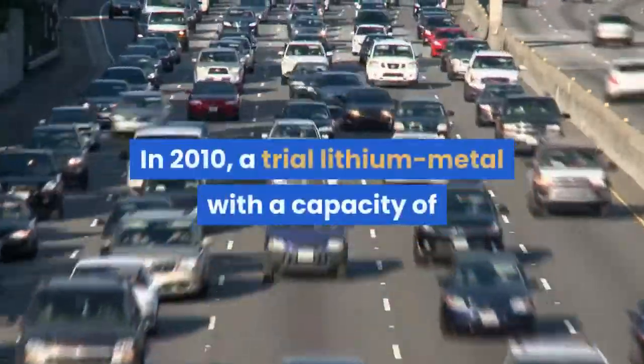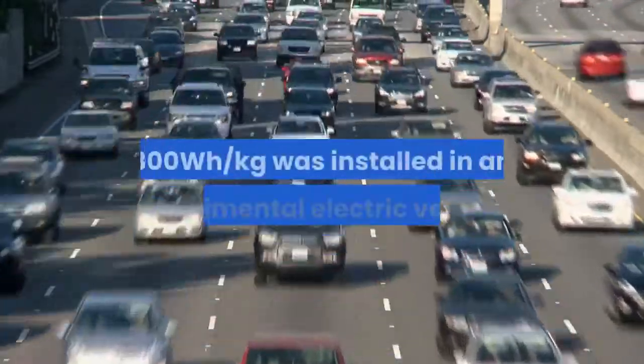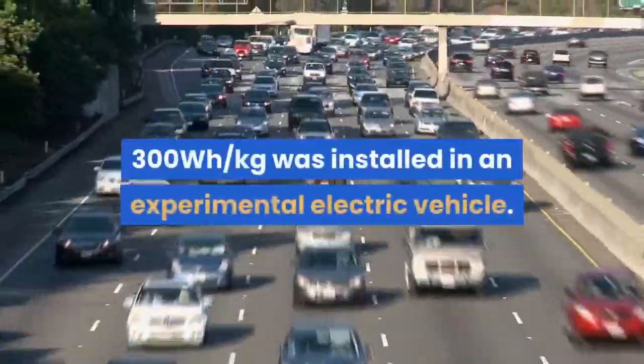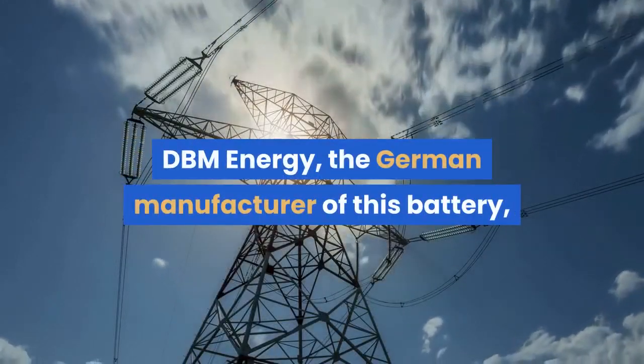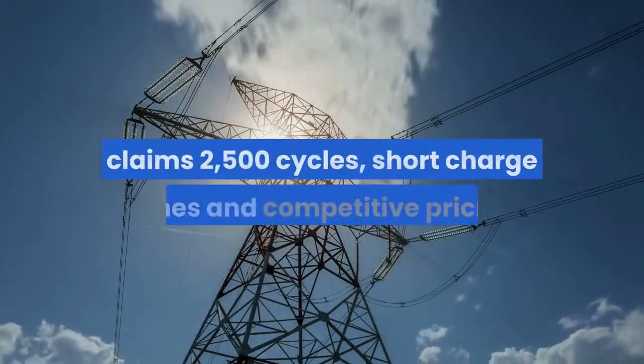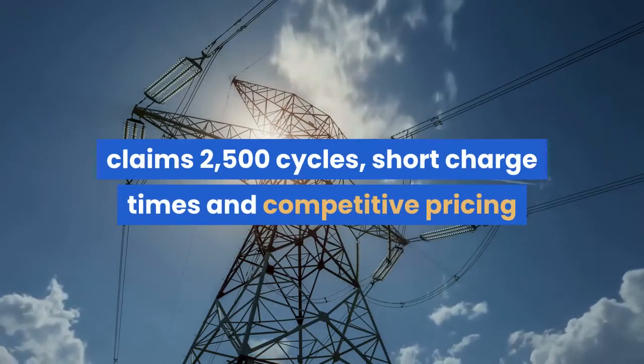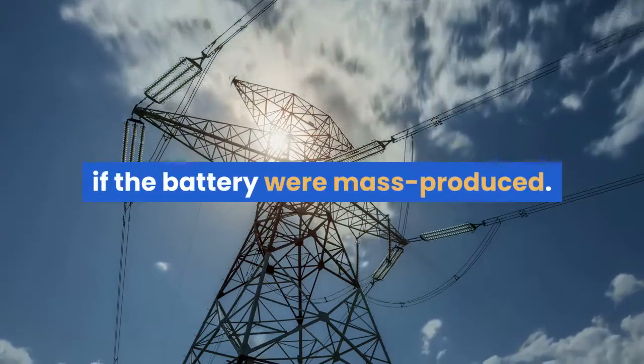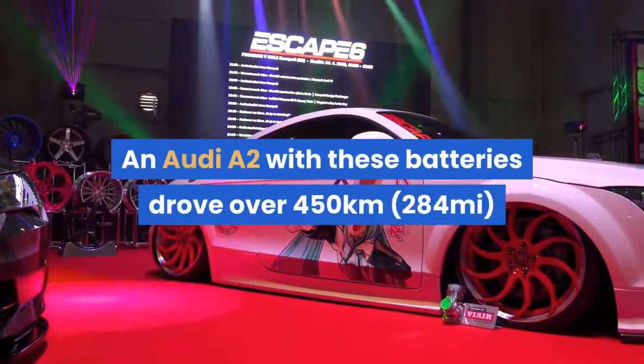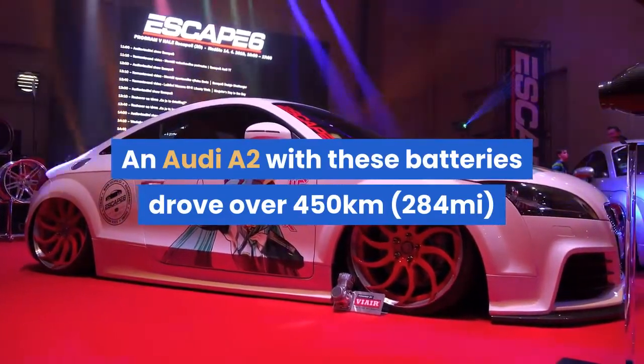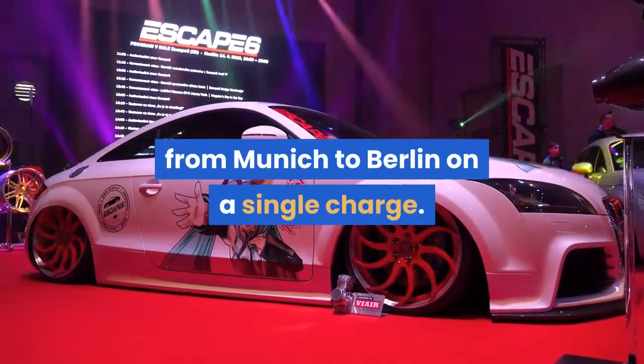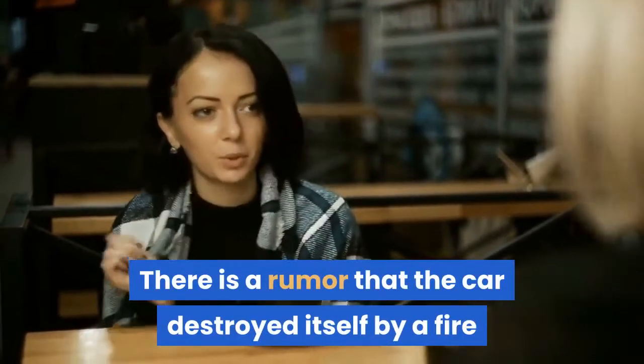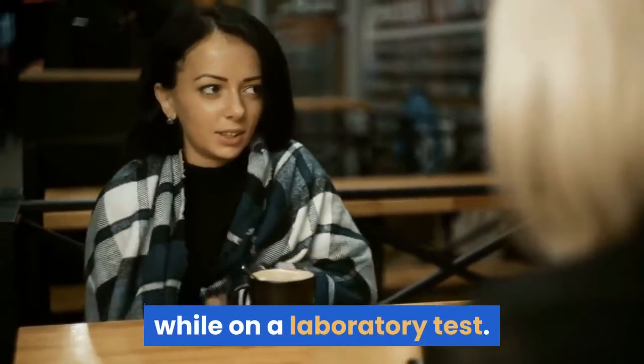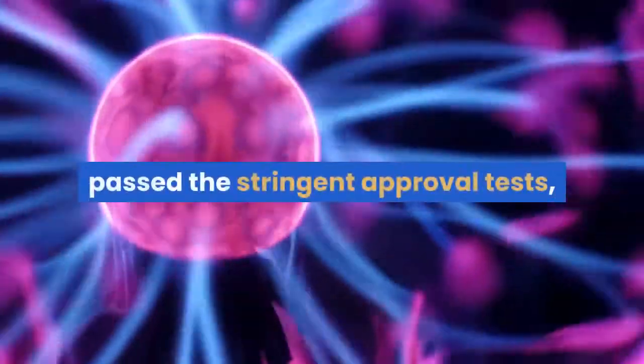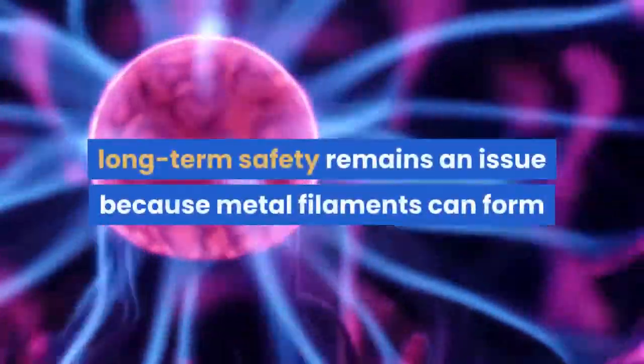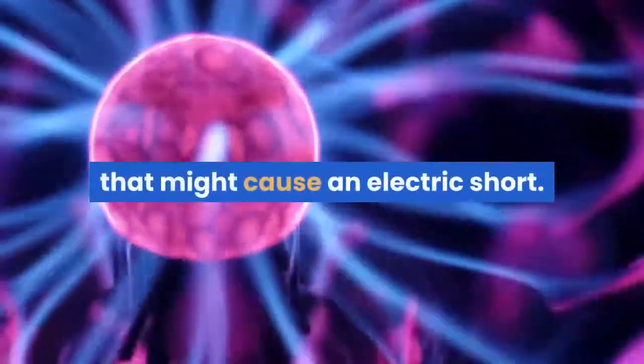In 2010, a trial lithium metal battery with a capacity of 300 watt-hours per kilogram was installed in an experimental electric vehicle. DBM Energy, the German manufacturer of this battery, claims 2,500 cycles, short charge times and competitive pricing if the battery were mass-produced. An Audi A2 with these batteries drove over 450 kilometers, 284 miles, from Munich to Berlin on a single charge. There is a rumor that the car destroyed itself by a fire while on a laboratory test. Although the lithium metal batteries passed the stringent approval tests, long-term safety remains an issue because metal filaments can form that might cause an electric short.